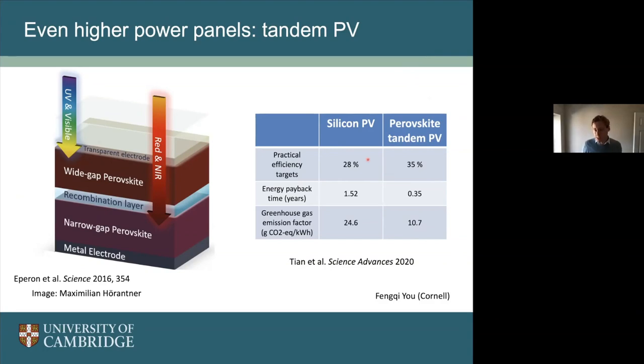For example, silicon is projected to reach about 28% efficiency. These tandems can reach 35%. This doesn't sound like much of an improvement in efficiency, but if it's operating for 30 years, producing power for that whole time, it's a huge amount of energy gain, and therefore the cost of that electricity comes down really quite dramatically. So this actually is a very important improvement in performance.